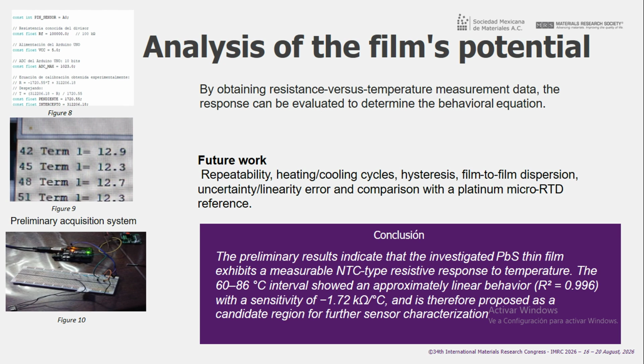Analysis of the film's potential. In figure 8 is the preliminary acquisition system. By obtaining resistance versus temperature measurement data, the response can be evaluated to determine the behavior equation. Future work: repeatability, heating and cooling cycles, hysteresis, film-to-film dispersion, uncertainty, linearity error, and comparison with a platinum micro RTD reference.